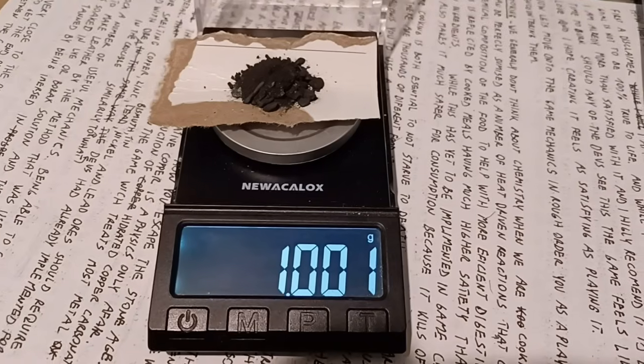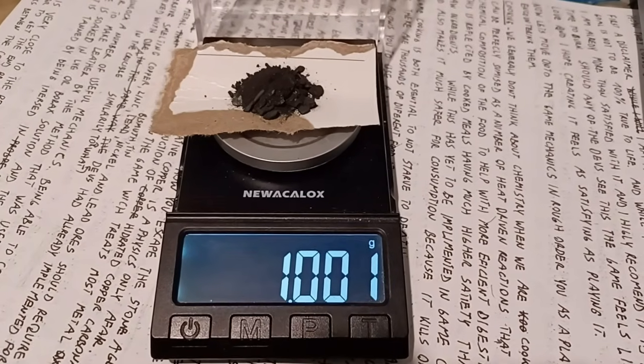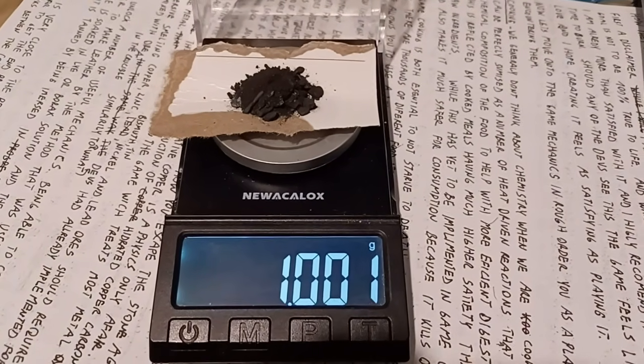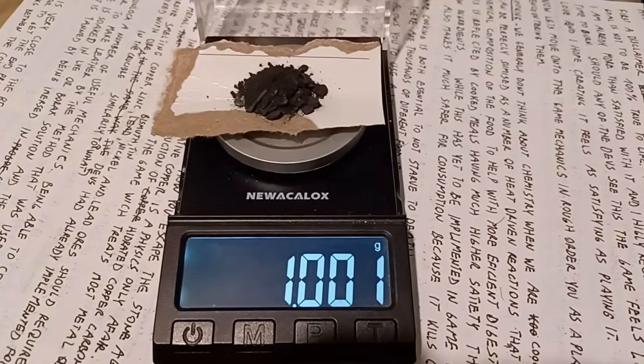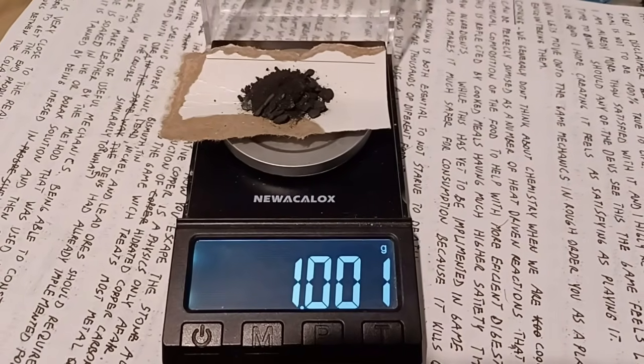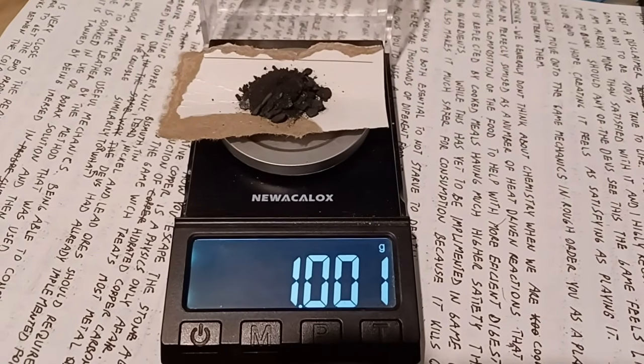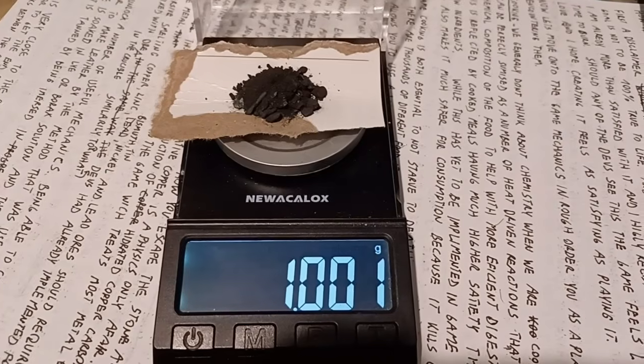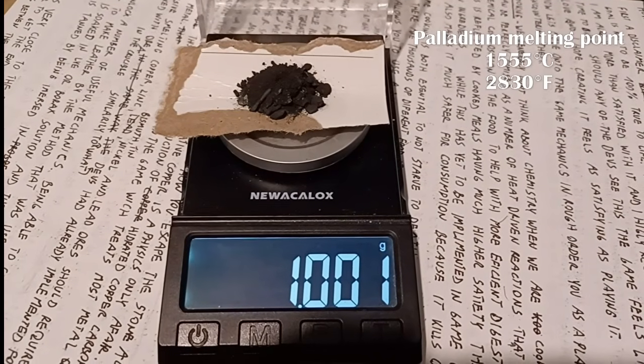I crushed the green slag and was positively surprised to find there were no silver beads in it. When I melt silver with a MAP gas torch, I never get this good of a separation. Now let's move to something a MAP gas torch won't melt. Palladium melts at 1828 Kelvin, which is high but still nothing compared to the max possible temperature of the arc.